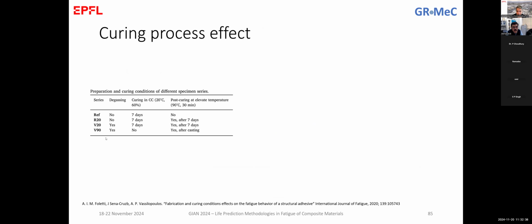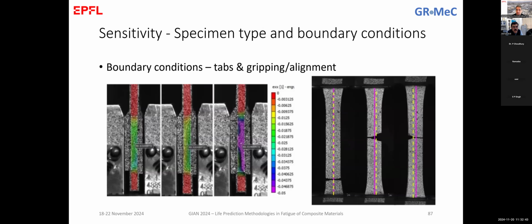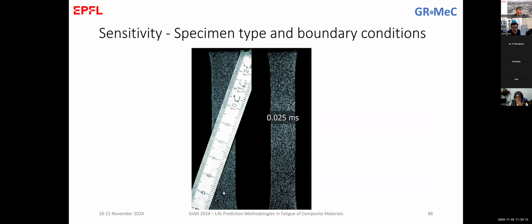I think the gauge length also plays a role in this. Of course. Now working with smaller gauge length for high stiffness, very small. Of course, you will see also the comparison between the type 1, type 2, and type 4 specimens that we did. So here, again, the alignment plays a significant role. We've seen that if there is a slight misalignment of the specimens, like what we have in the middle or on the left, we had a kind of bending in the specimen, and we always had a small piece that was coming out of the specimen during failure. There is a footage here.